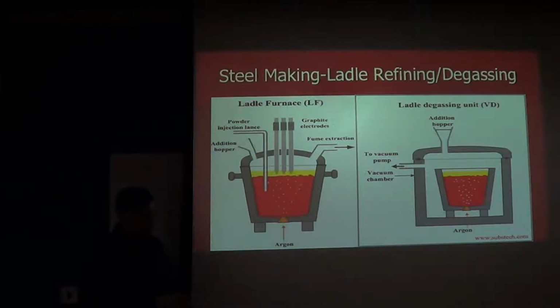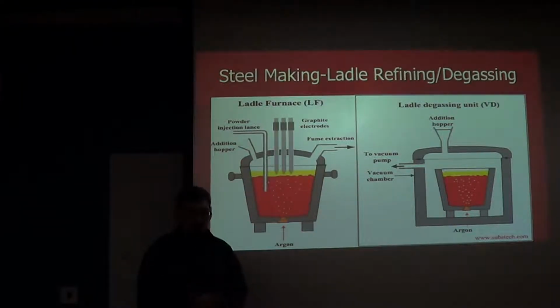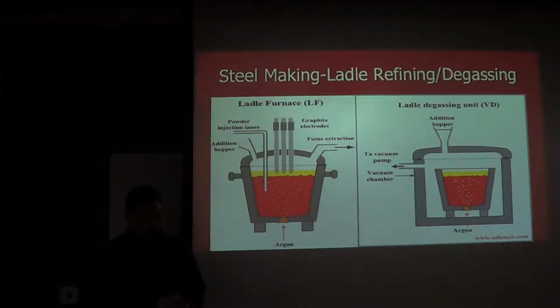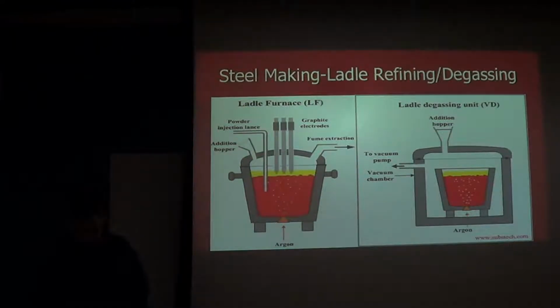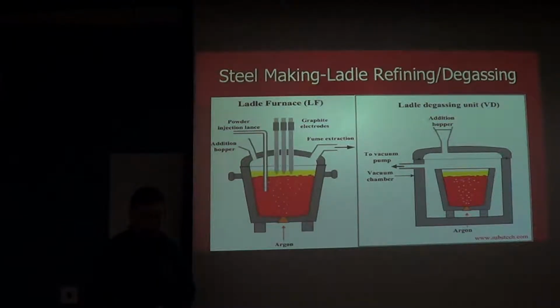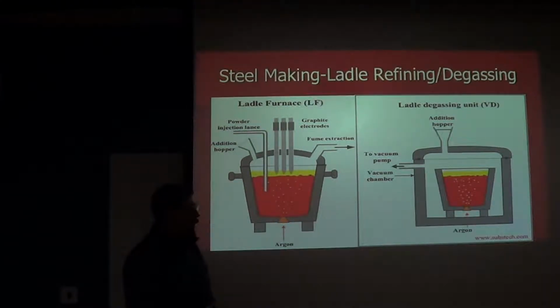And that stream of liquid metal, which is typically just a few inches in diameter, will essentially atomize because it's being exposed to this vacuum environment, and it allows for a really rapid and complete removal of dissolved gases from the liquid metal. I know of at least one shop here in the United States that does that. I know there are others around the world that do that. That's a technique that's used widely in very, very large ingot production.